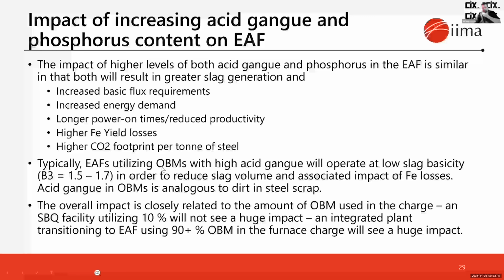Most EAFs utilizing ore-based metallics with high acid gangue content tend to operate at low slag basicity, typically a B3 of 1.5 to 1.7, in order to reduce the slag volume and the associated impact of the iron losses. And of course, it depends how much of these OBMs you're using in the charge. A lot of existing EAF operations, even those producing flat products, might use anywhere from 10 to 40% OBMs, depending on the grade that's being made. The integrated plants that are looking to transition are all planning on using about 90% OBMs in the furnace charge. So the impact on them is much higher.